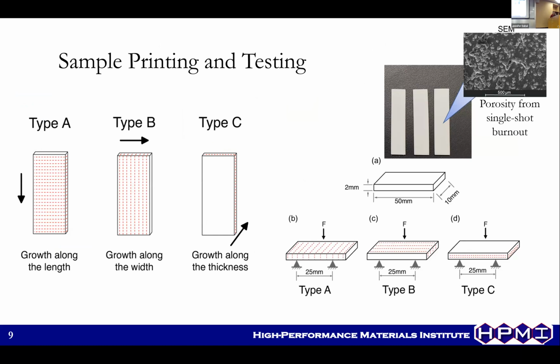So we want to understand the fundamentals of 3D printing. When you do 3D printing, you can do it in different ways. We studied three different ways of additive manufacturing: type A, type B, and type C, which is growth along length, width, and thickness. Then we studied them in 3-point bend flexural testing with those support beams, as you can see here.